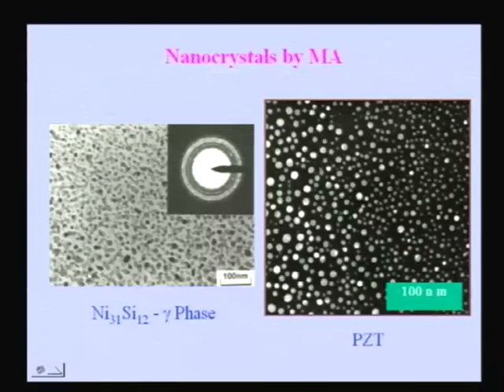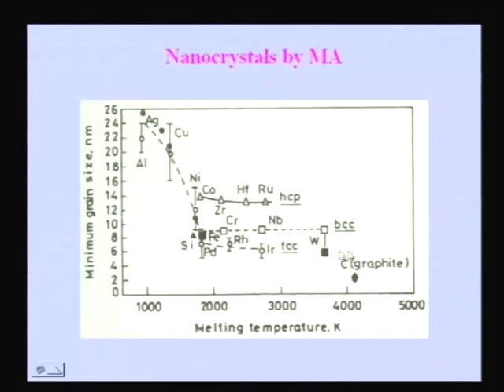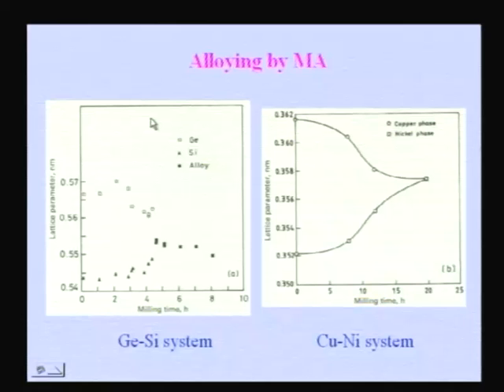Nanocrystals one can make. This is in the metallic system, this is in the oxide system, PZT. The crystal size that you can achieve by mechanical alloying is always a function of melting point. The higher the melting point, for example graphite and tungsten have very high melting points, one can achieve very low crystal size. Whereas aluminium, copper, silver cannot reach very low crystallite size. You have a high crystallite size. That is one.